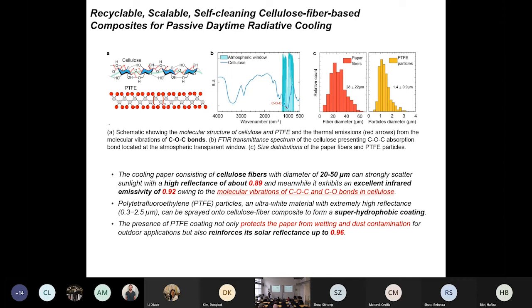Here we found that recycled paper, the cellulose fibers, has really high reflectance of visible and infrared light, up to 89%. It may not be good. During the past 3 years, a few groups in America and China have studied passive cooling a lot. One successful one is the white cooling paint by a group at Purdue University. That white paint can reflect 99.9% of sunlight. This one is only 89%. It's not good at all, I admit. But considering the material itself is totally low-cost, and the raw material simply comes from recycled paper, daily life waste material.